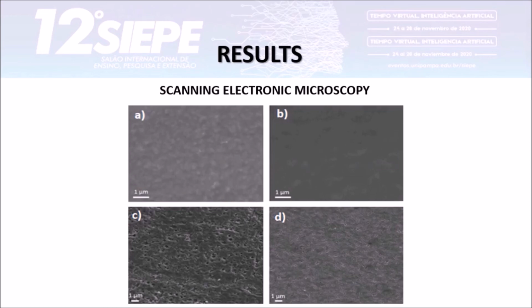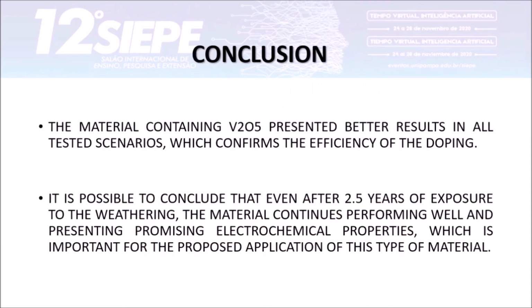So we can conclude the material containing vanadium pentoxide presented better results in all tested scenarios. It confirms the efficiency of the doping. It is also possible to conclude that even after 2.5 years of exposure to weathering, the material continues performing well and presenting promising electrochemical properties, which is important for the proposed application of this type of material.